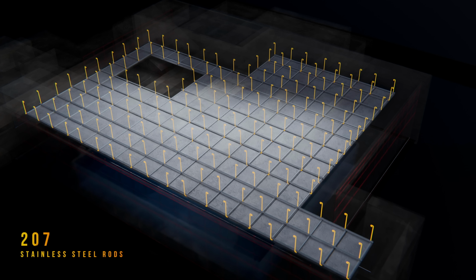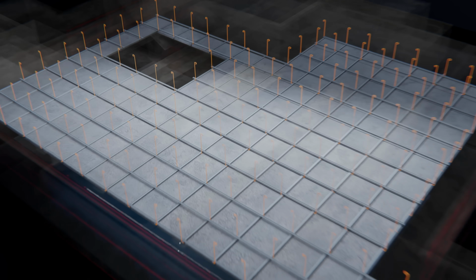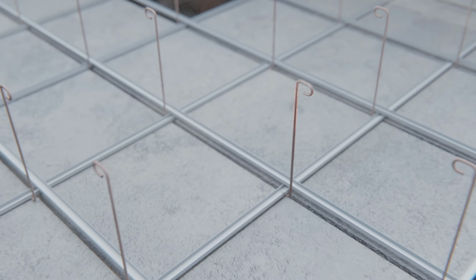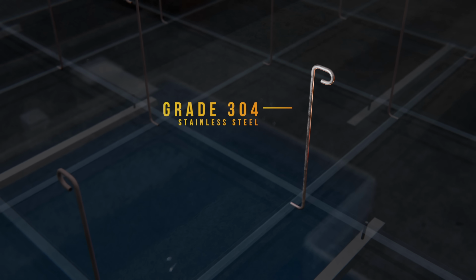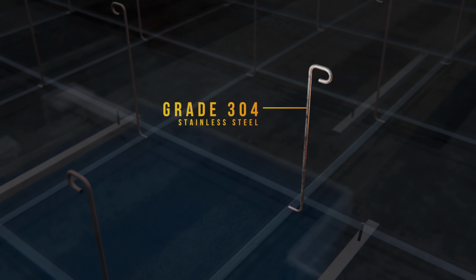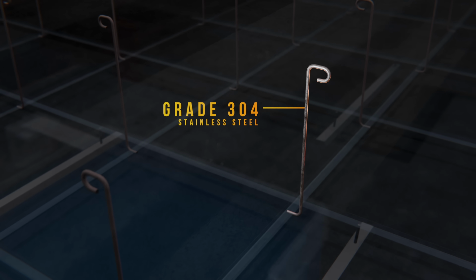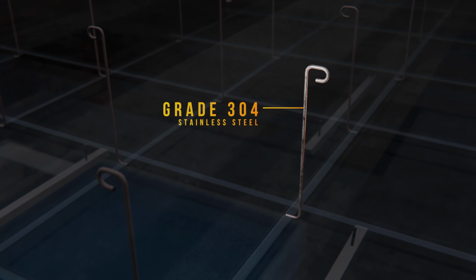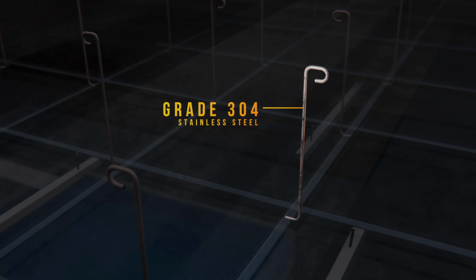Investigators would quickly identify the culprit. The stainless steel rods that held up the ceiling panels had been silently corroding away, setting off a sequence of events that would end in collapse. This was completely unexpected. Grade 304, the most commonly used stainless steel, was chosen for the rods precisely because of its excellent resistance to corrosion.